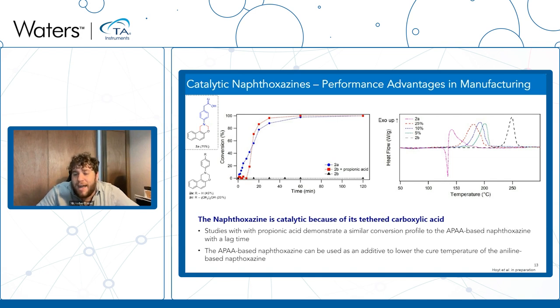So here in the dotted black line, you see the data you saw on the previous slide, same with the dotted pink line. And these exotherms that you see in between are us slowly adding in this catalytic naphthoxazine and dramatically reducing the cure temperature of the material. So here we've shown that we can leverage the bio-derived functionality of a material to reduce its cure temperature and thus have benefits in manufacturing.